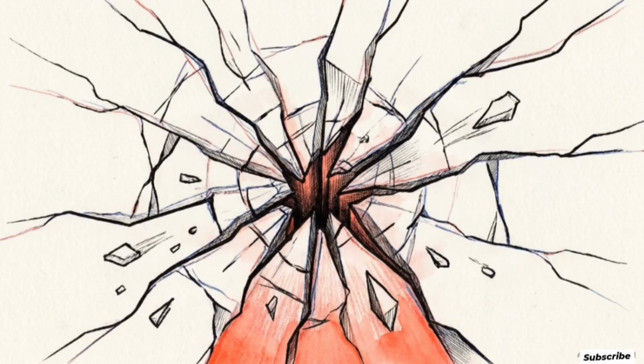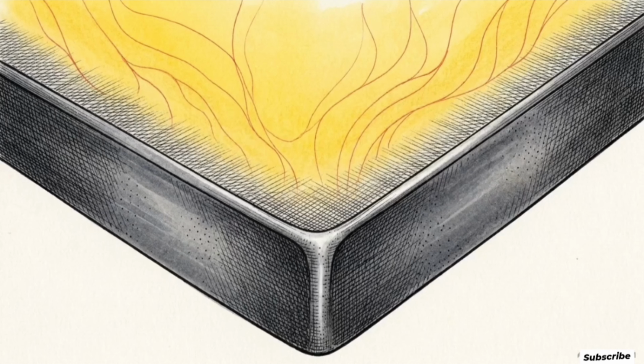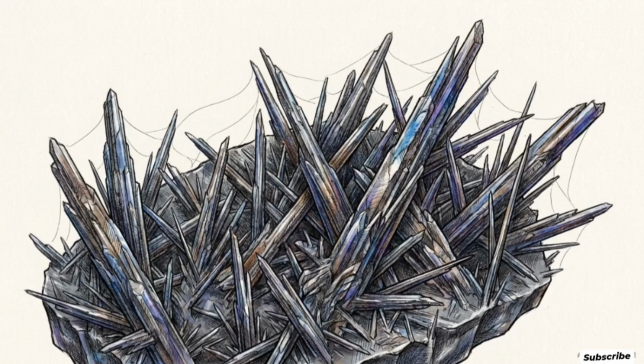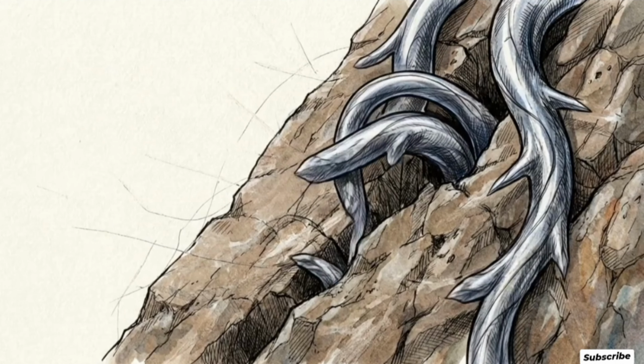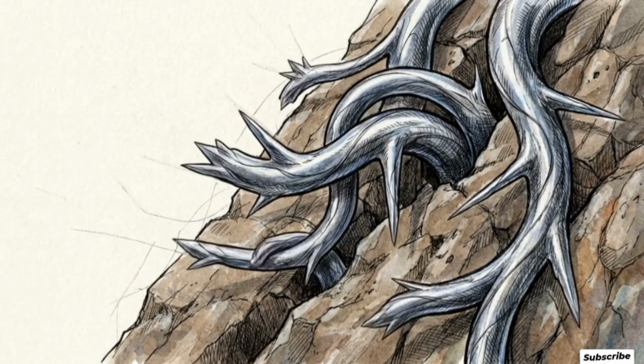Once the ceramic is fractured, the battery's structural integrity is gone, clearing a path for a much more aggressive failure. During charging, high current density causes lithium metal to deposit onto the anode, but it doesn't plate in a smooth layer. It forms jagged, uneven deposits. These deposits grow into thin, metallic filaments called lithium dendrites.